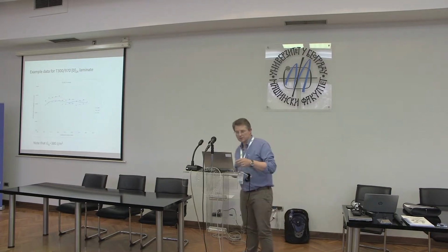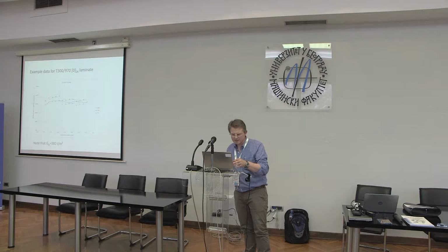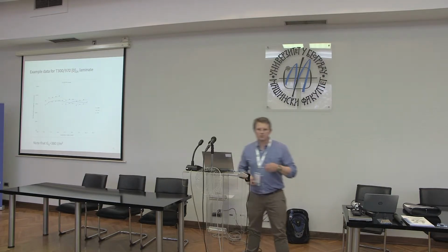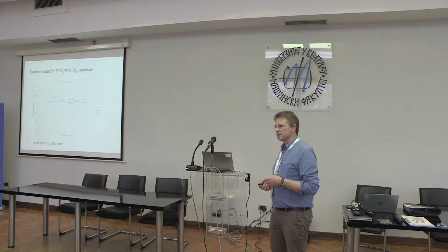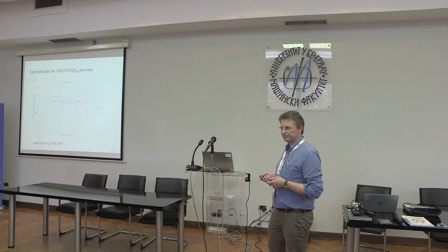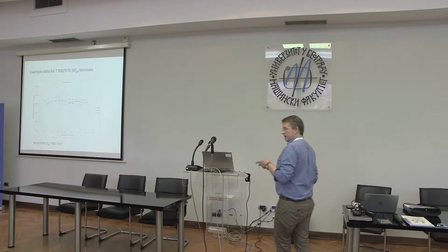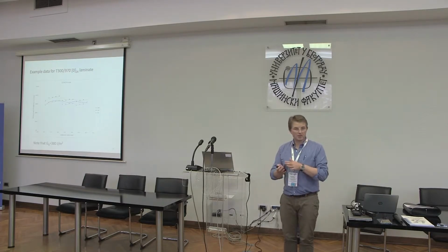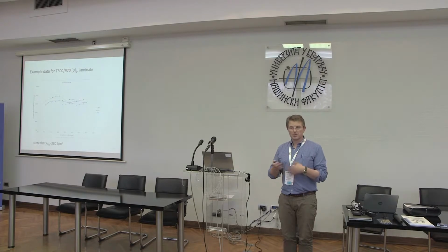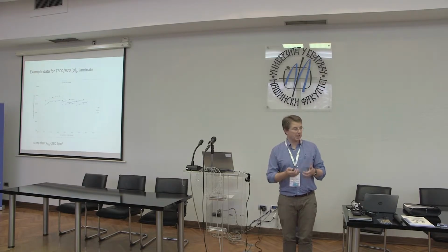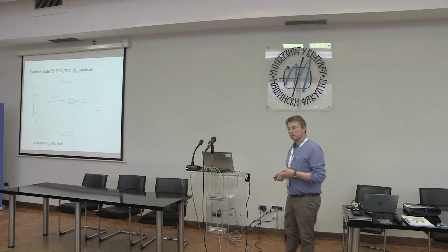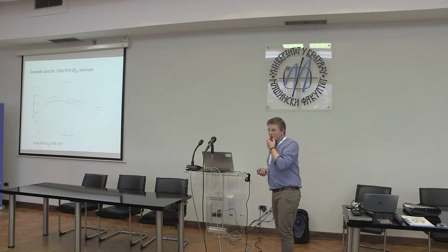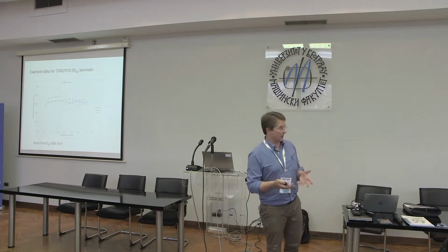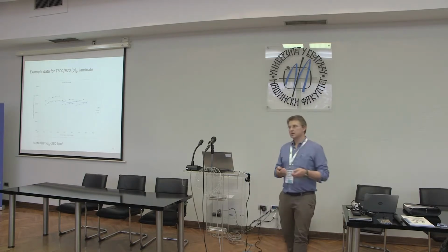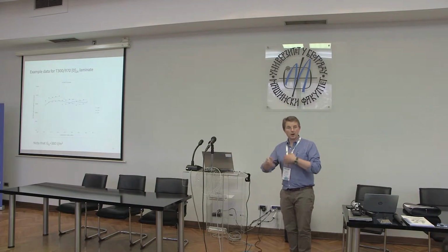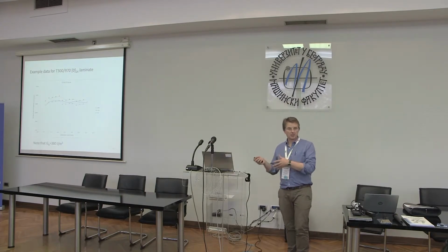It's probably worth noting with this experiment, we can see that the mode 2 fracture resistance is about 4 times the mode 1 fracture resistance. Okay? So what we're saying here is that when we perform this fracture experiment in mode 2, we're dissipating approximately 4 times as much energy than when we load in mode 1. So it's interesting, why is that the case? What's happening to this extra energy? What's going on micromechanics-wise at the crack tip to dissipate so much more energy?